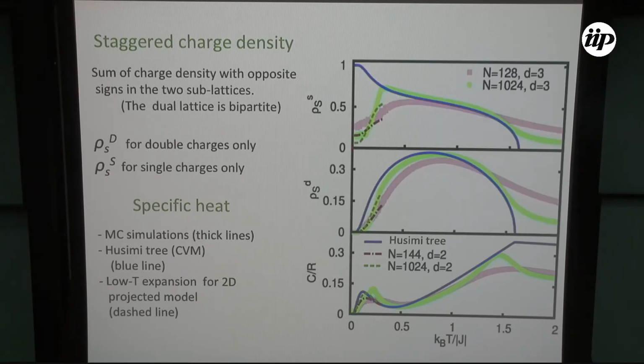And this is what you get. So this is the staggered density for single charges and the staggered density for double charges. And you see what's happening, let me start with the single charges. Again, the color code is the same. This line corresponds to the infinite system size limit, and this is for 2 lattice sizes. So this is for 128 spins, or for 1,024 spins. You see that this feature moves to lower temperatures as you increase the system size, and when you're in the infinite size, it's just a very sharp step.